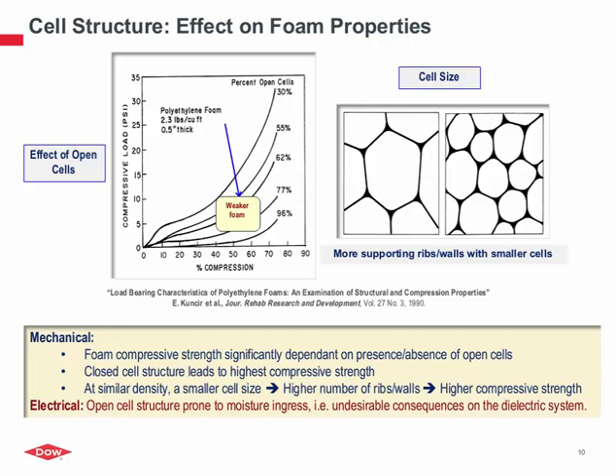If one has a large cell at the same unit surface or cross-sectional area, larger cells mean fewer supporting ribs or walls of these cells. With smaller cells, you can see there is much more supporting structure overall, and that's what brings about the higher compressive characteristics. So from a mechanical standpoint, the foam compressive strength is significantly dependent on the presence or absence of open cells, and also at a similar density, a smaller cell size would result in a higher number of supporting walls. That means higher compressive strength.